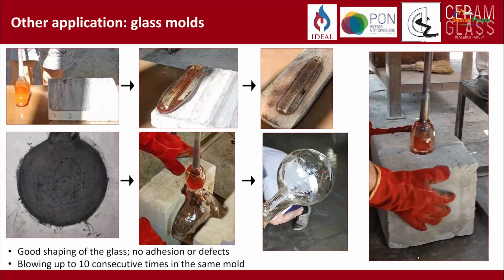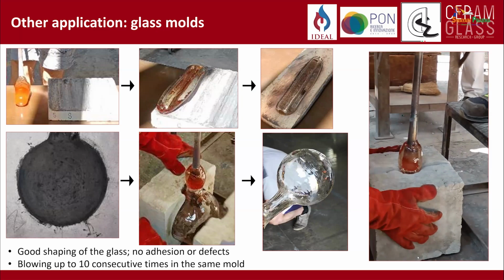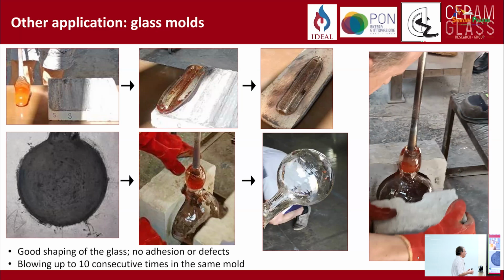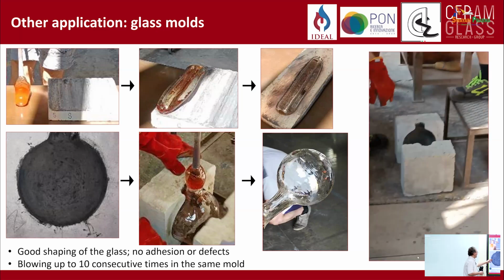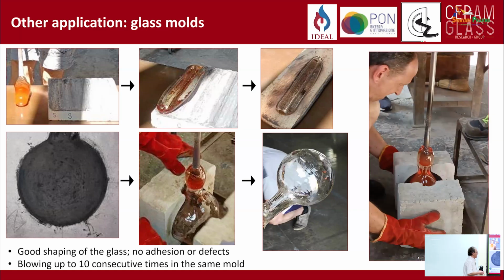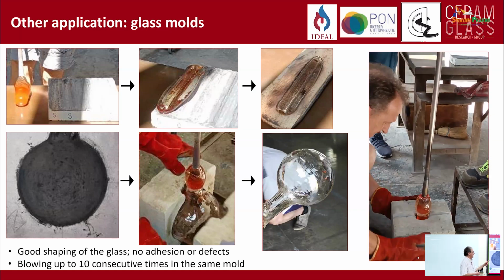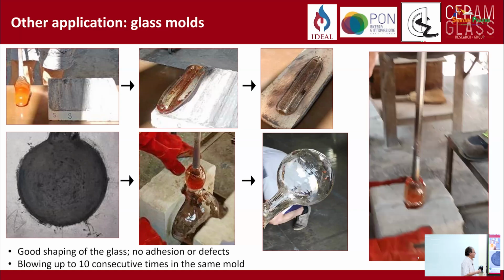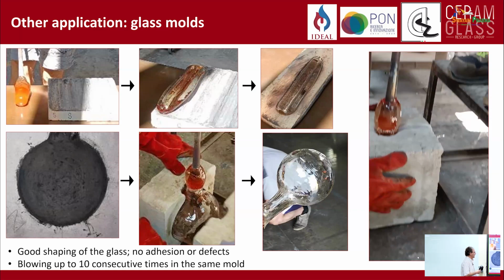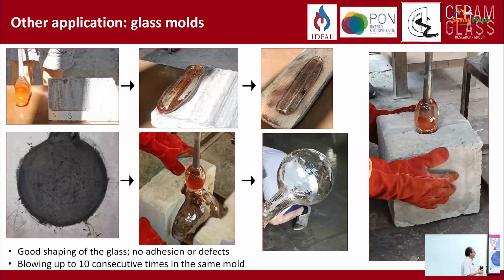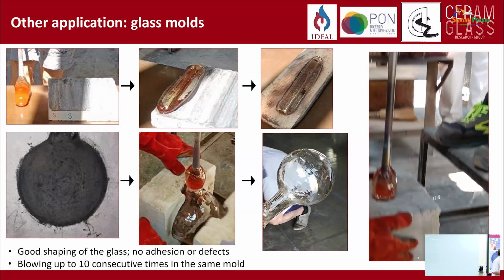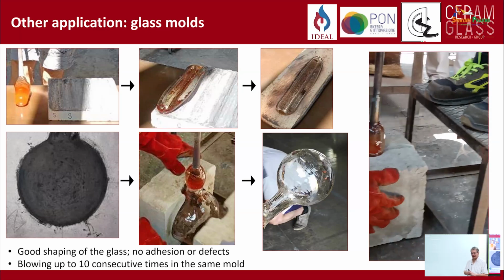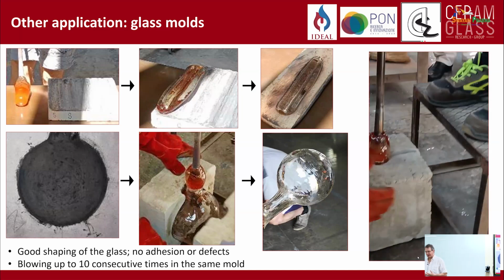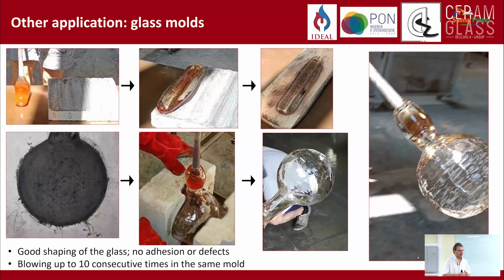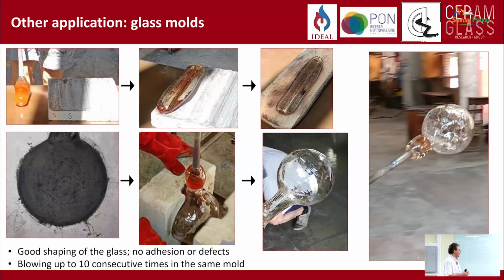Due to the limited resolution for this specific printer that we used, 5 millimeters voxel size, we have some precision issues, meaning that it is not easy to have a rotating part inside the mold because there are still some defects in the inner surface of the mold. But you can see that we can have lustrous surfaces, fully transparent glass. So if we further improve the quality of the mold, this is a suitable approach for making art objects.